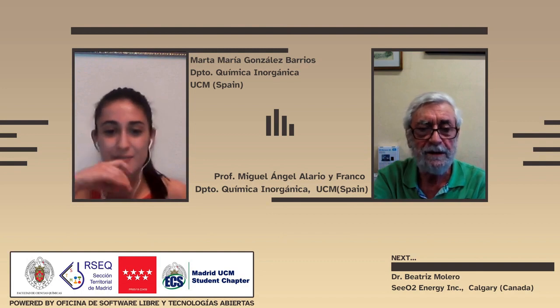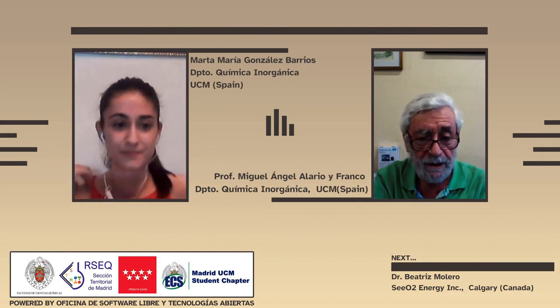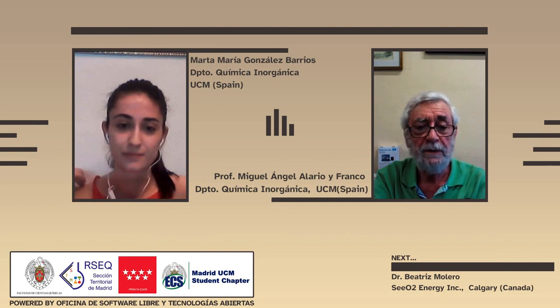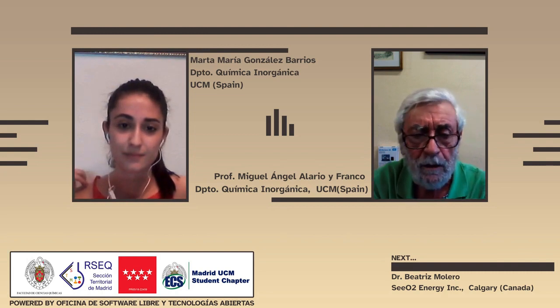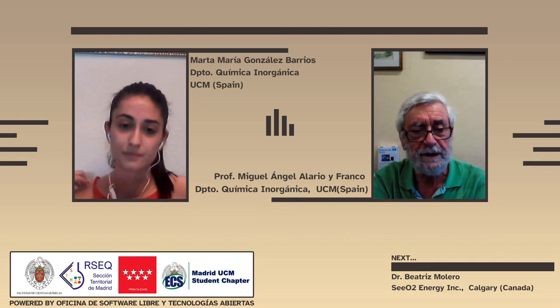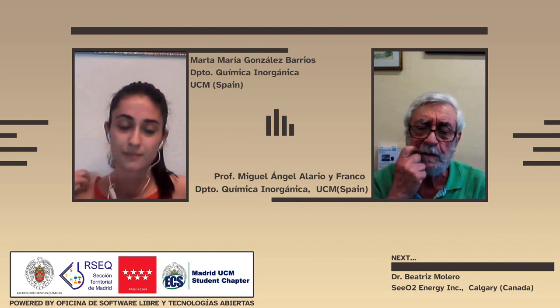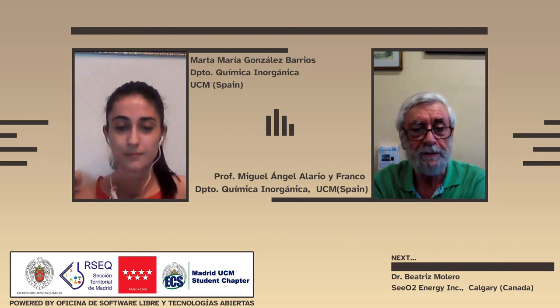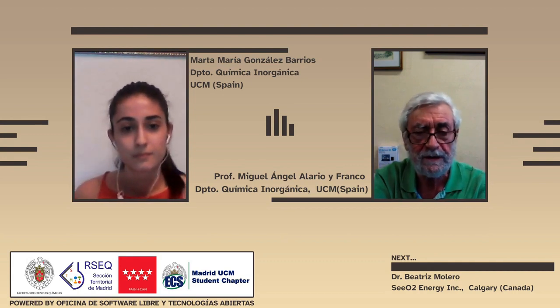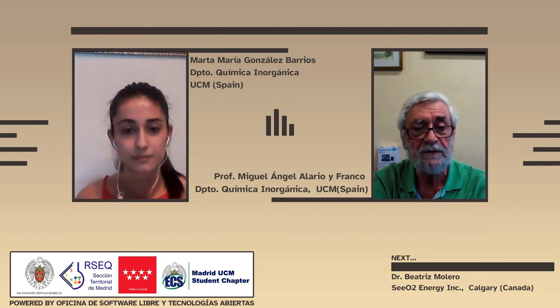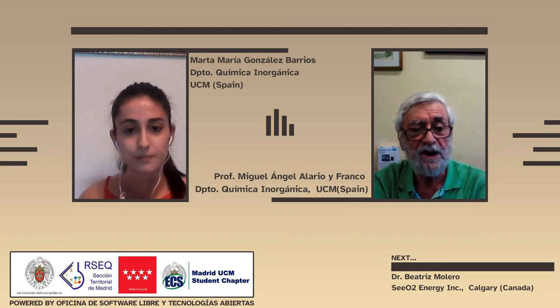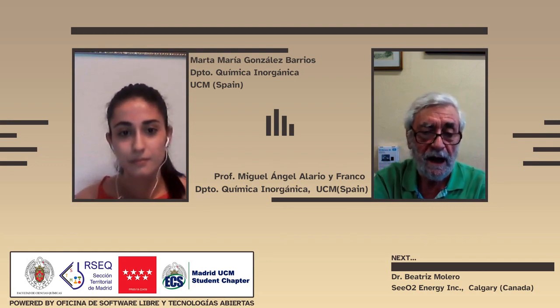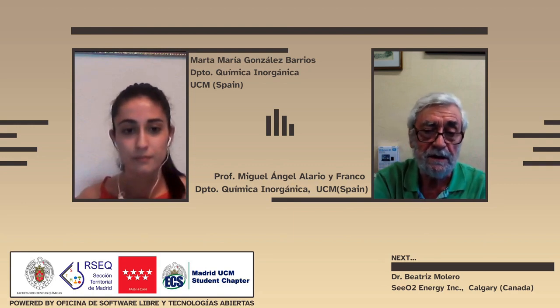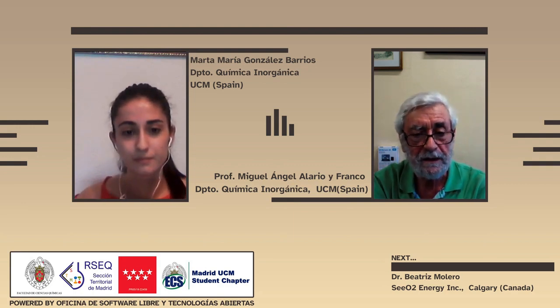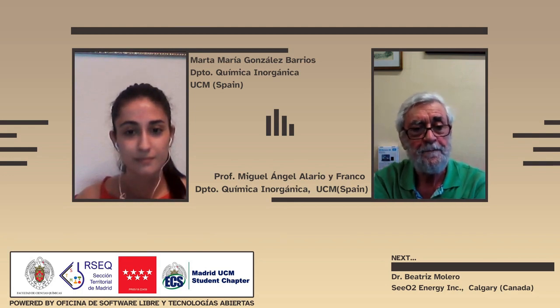But there are plenty of descriptions of the BCS theory, which was really a little forgotten because the cuprates did not work. The theory doesn't explain the superconductivity in cuprates, for reasons which are also complex, but the hydrides do, as I've shown you. So, in fact, it is like a renaissance of the BCS theory, and the highest Tcs obtained, certainly under pressure, can be explained and actually predicted by the BCS theory.